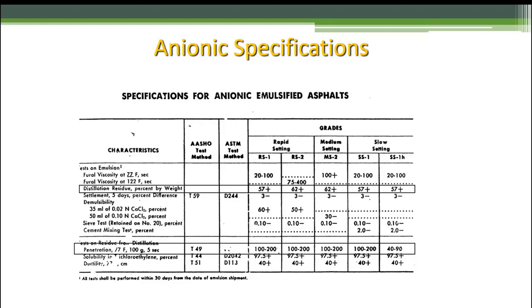Last thing on this slide, at the bottom boxed in there, is the penetration. That's the residue test. What's the residue? The asphalt cement. So you can see in the first four columns, the residue, the asphalt, is a pen graded asphalt at 100 to 200 penetration. So it's 100 to 200 pen asphalt, except for that last one, SS1H. The residual in that SS1H is a 40 to 90 pen asphalt, much stiffer, right?